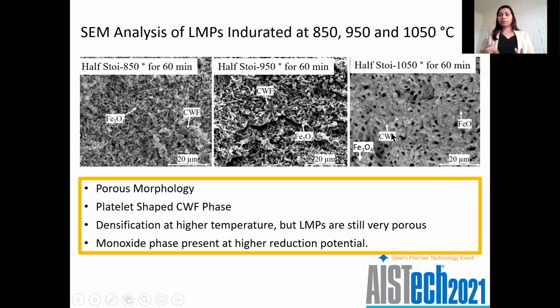Now, all these three experiments were conducted at a fixed CO2 by CO ratio of 4:1. Obviously, at fixed CO2 by CO, when we go to a higher temperature, the reduction potential is higher. And therefore, we see some of the magnetite to wustite reduction as well. But even with the presence of this denser FeO phase, we can see that the overall microstructure is quite porous with lots of open pores. Other than the CWF phase, we also saw some calciferrite phase like C2F, 2CaO.Fe2O3. They started to form at the beginning of the reaction, and then the percentage decreased with progress of the reaction.